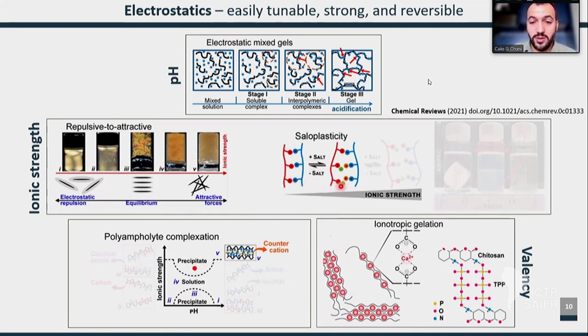Supramolecular. So the small electrolytes here, they are going to compensate the charges. So we're increasing the doping level. So the charges are still compensated, but not by the other polyelectrolytes, but by the counter ions, right? The counter anion and the counter cation. And as you put more salt, there is fully extrinsic charge compensation. So all charges are being compensated, matched by the small electrolytes.